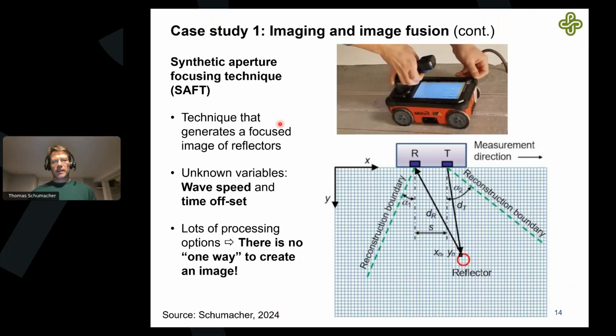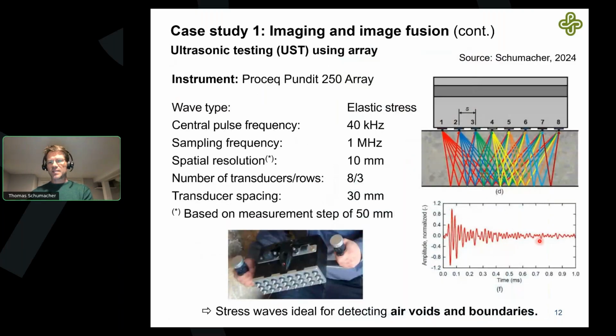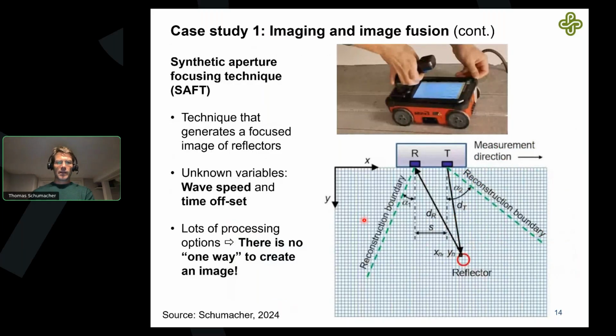The way we do the imaging is called the synthetic aperture focusing technique, or SAFT. That's the technique that takes these wiggly, individual signals and turns them into an actual cross section. I don't want to go too much into detail here, but the idea is that for one position, shown here, we divide up the cross section, so we have measurement direction and then depth on the vertical axis. This is shown for just a simple two sensor setup.